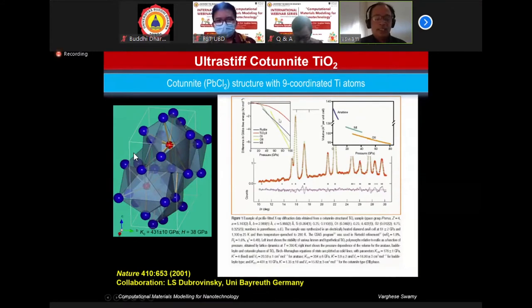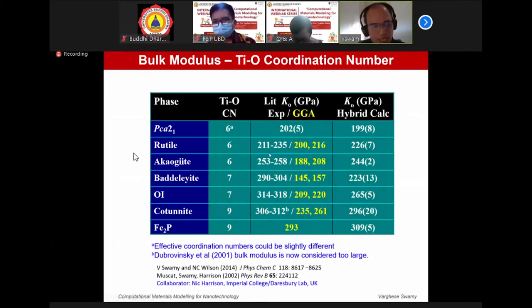Now, I said it was a combination of both experiment and computational studies that gave us all these results. Here, I'm showing a table which shows various titanium dioxide phases and the titanium-oxygen coordination polyhedral number here, the coordination number here. And the rightmost entry on this column is the bulk modulus computed using quantum mechanical methods. And in between, we have both experiment and another computational approach, which is another version of quantum mechanical calculation. You can see that in good agreement with the experimental data given here, we were able to calculate the bulk moduli for all the phases in the TiO2 system.